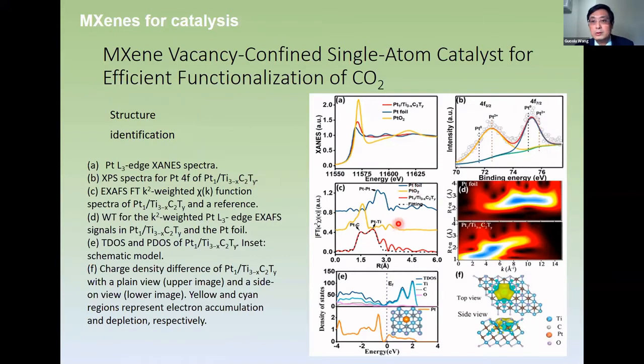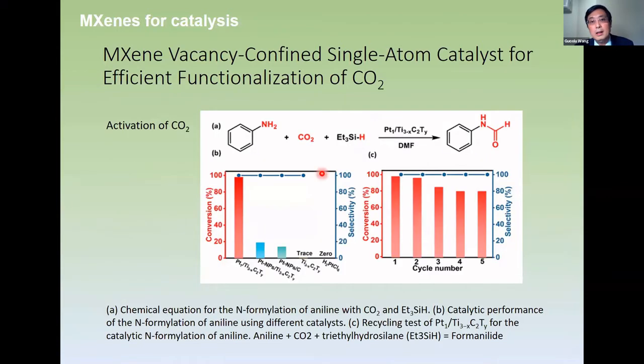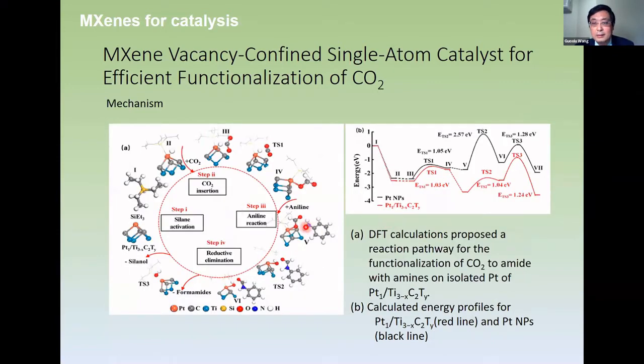And similarly, we use the synchrotron to confirm the Pt single atoms are positively charged. That means we successfully obtained the platinum single atoms. And we apply this single atom Pt on the surface of MXene as the catalyst for functionalization of carbon dioxide. We put aniline and carbon dioxide and triethylhydrosilane, and then we successfully obtained a chemical called formamide. So this is a very complicated catalytic chemical reaction, and also we did DFT calculations that explain the mechanism we proposed. So this is MXene.